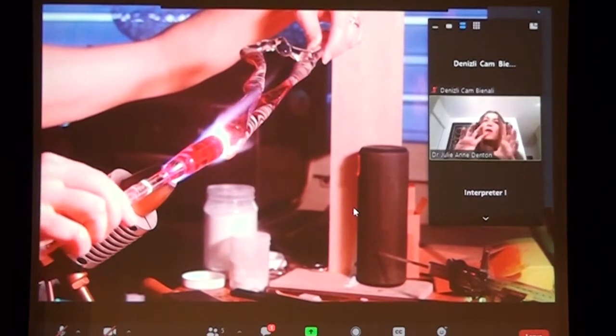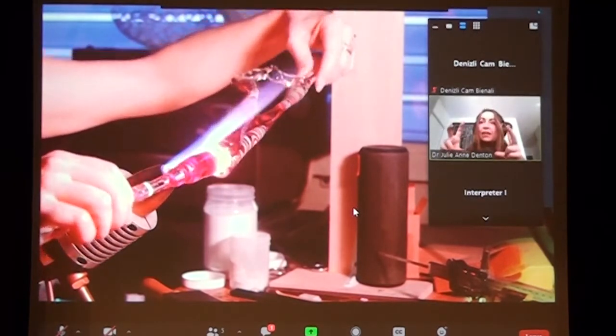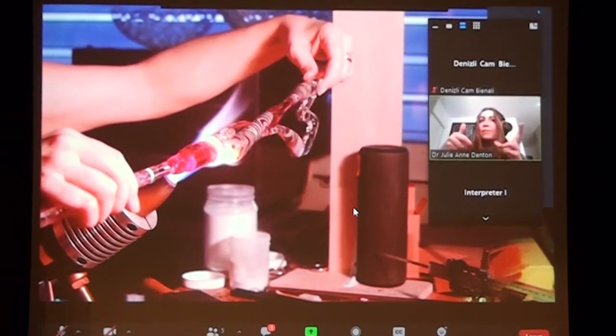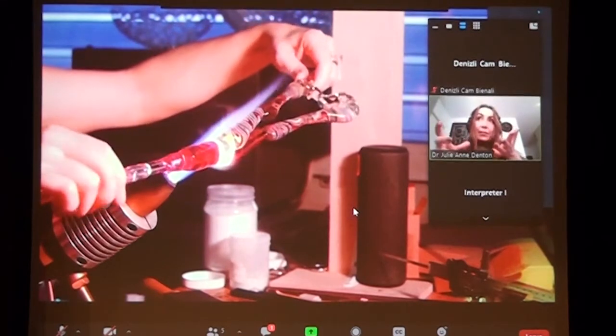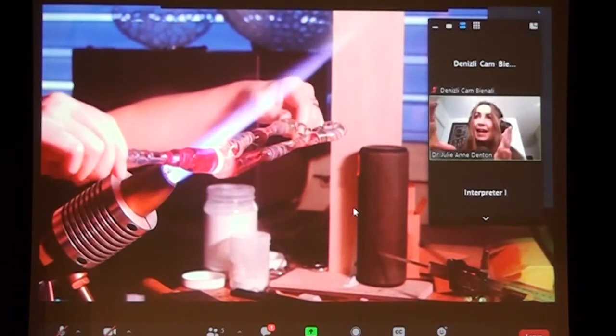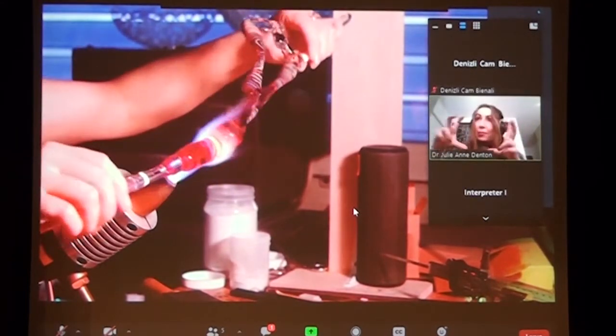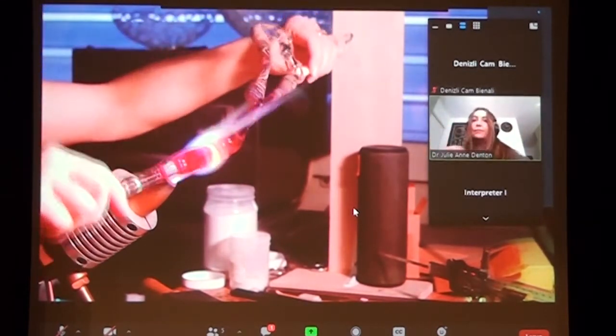And so maybe you didn't see, before I realized I'd forgotten the tail, I actually put quite a lot of propane in my flame, and this was to help anneal the lips before I moved on to make the rest of the body. And this is very important in a flame worker's toolkit, to anneal as you go along.